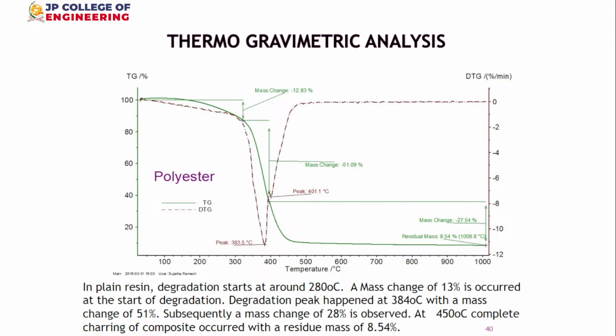So from this graph you can obtain a complete picture of the degradation, including the starting temperature. For example, in the plain resin, it started at 280 degrees. See the bottom script: 280 degrees, it should be degrees centigrade. Peak degradation occurs at 384, and almost at 450 degrees centigrade it is completely degraded. So you can get a complete thermal history, how the degradation starts and then progresses. Next slide, please.